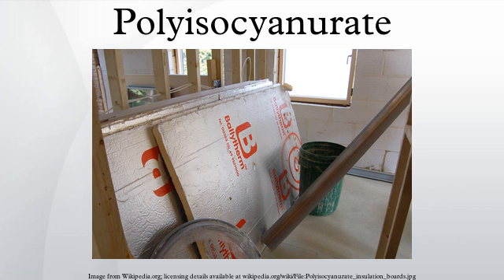Manufacturing: the reaction of MDI and polyol takes place at higher temperatures compared with the reaction temperature for the manufacture of PUR. At these elevated temperatures and in the presence of specific catalysts, MDI will first react with itself, producing a stiff ring molecule, which is a reactive intermediate. Remaining MDI and the trimer react with polyol to form a complex polyurethane-isocyanurate polymer, which is foamed in the presence of a suitable blowing agent.